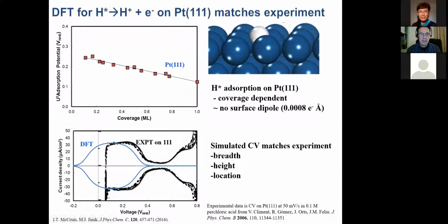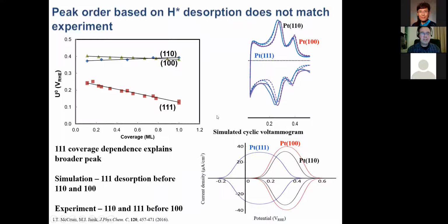And we can match the height of this peak. We essentially get the breadth and the curvature right. And you can argue we're off by about 0.1 volts or 0.1 electron volts, 10 kilojoules per mole, which is pretty good for quantum chemistry. So now we repeat that same process on two other surfaces, 100 and 110.